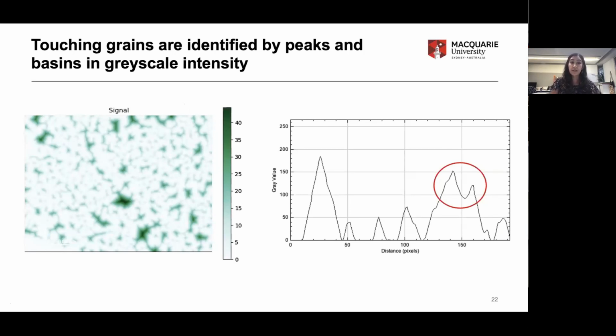So I tried an approach where I was able to identify touching grains, again by exploiting this grayscale intensity. Here I looked at where my nearest neighbor was. Essentially, these peaks correspond to the center of the grain, and when we fall to the bottom of that grayscale value, that's the grain boundary. In some cases, we end up with a saddle, and that's basically where we have two grains touching. The grayscale value hasn't fallen entirely to 0, but there is a clear dip here.